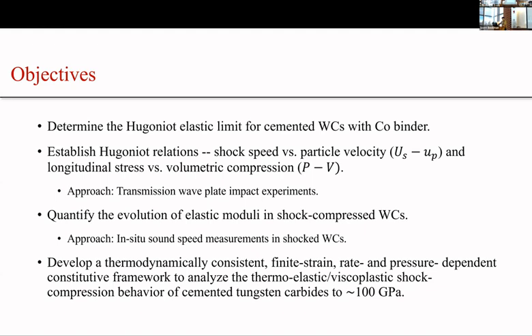The approach for achieving this goal is by conducting transmission wave plate impact experiments. We're also going to quantify the evolution of elastic moduli, which includes the longitudinal, bulk and shear moduli in the shock compressed tungsten carbide. To achieve that, we need to make in situ sound speed measurements in the shocked tungsten carbide. The last part of our research is focused on the development of a thermomechanical framework that describes the shock response of the cemented tungsten carbide under shock wave loading to 100 GPa.